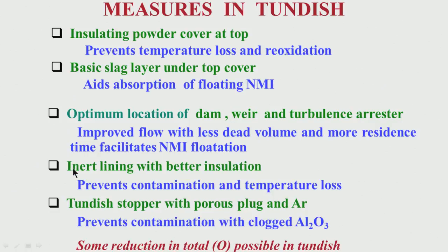Then as I was mentioning, we must have a good insulation, it should not cause contamination or temperature loss, this is very important. Then the Tundish stopper with porous plug and argon, this is very important, because this prevents contamination with clogged alumina. So as I was telling you,